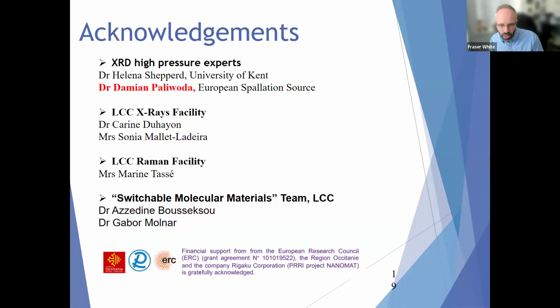Okay, next question is, how do you measure at low temperature and high pressure? So no, we did not. I understand your question, and maybe I was not clear. Actually, that was two different experiments. First of all, we study our crystal at low temperature, as you probably do on your diffractometers using the cryostream, and then we remove the cryostream, we load the crystal in the DAC, and then we mount the DAC and we do the high pressure experiments. So it's two different experiments. With this cell, we don't have the possibility to combine both.